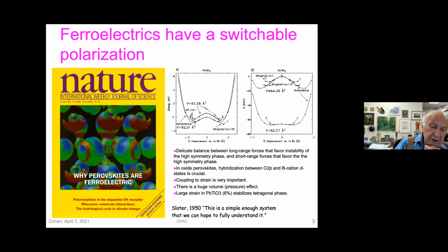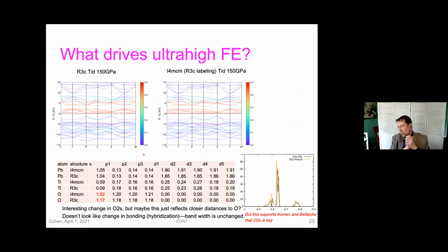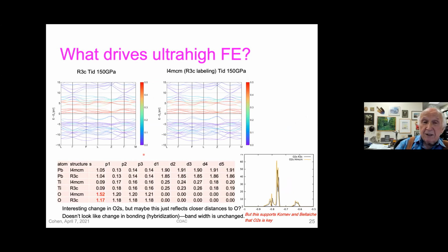Well, what one might have expected is some transitions under pressure. In general, electrons will get out of s orbitals and into d orbitals if they can. And so either the lead going from 6s to 5d or the titanium from 4s to 3d is what one would have expected. And the oxygen under pressure also would go up and maybe deplete, but you don't see the electron density going into the d orbitals, except on the titanium.